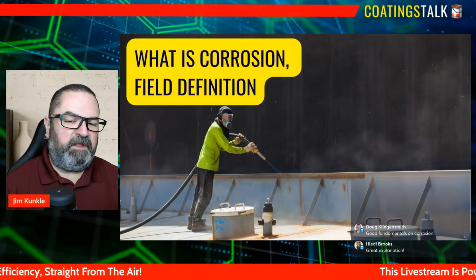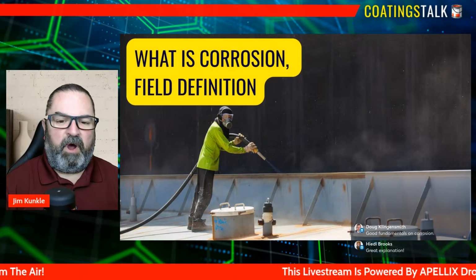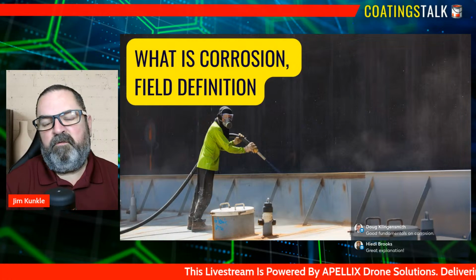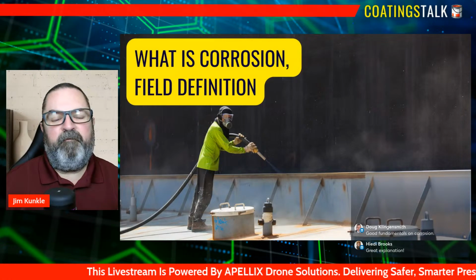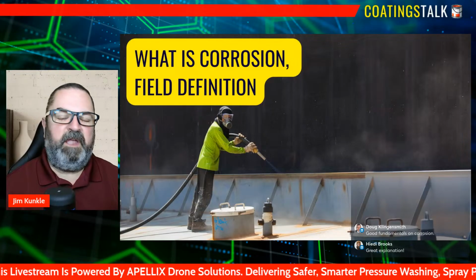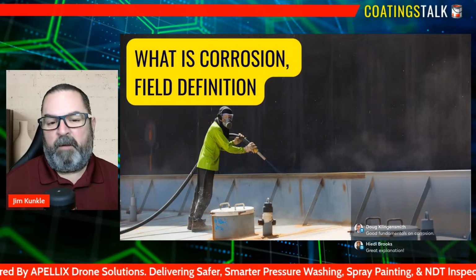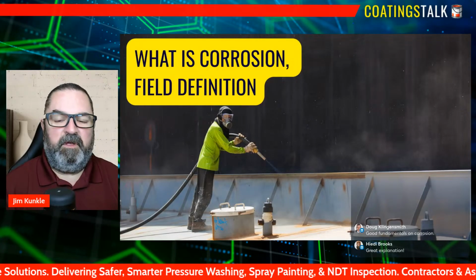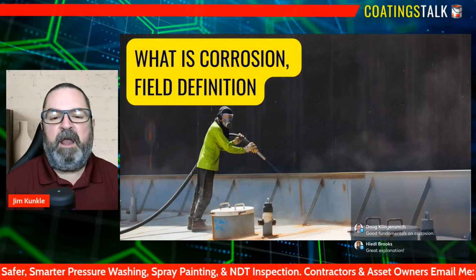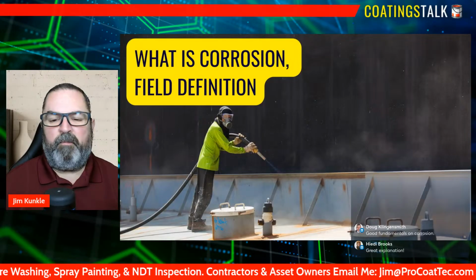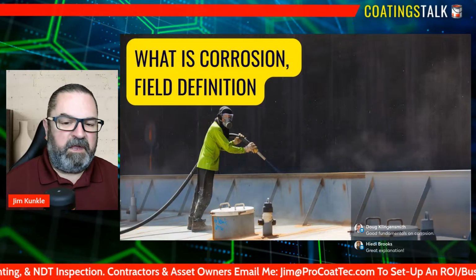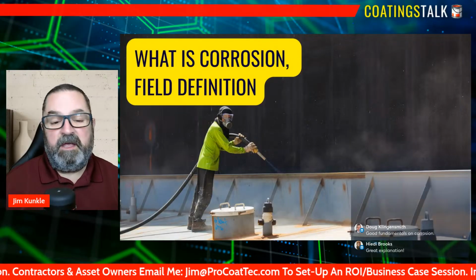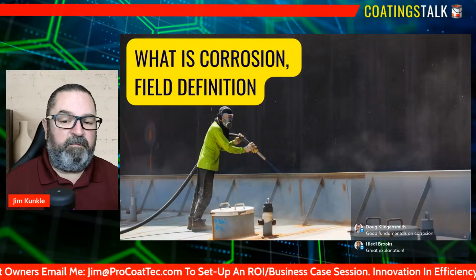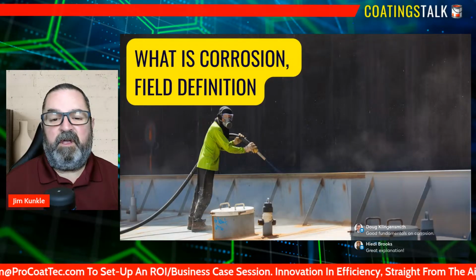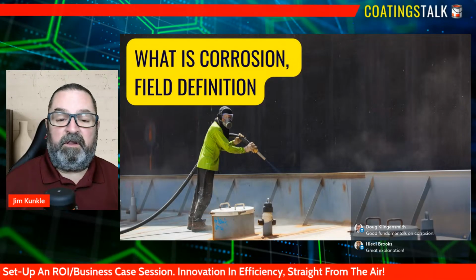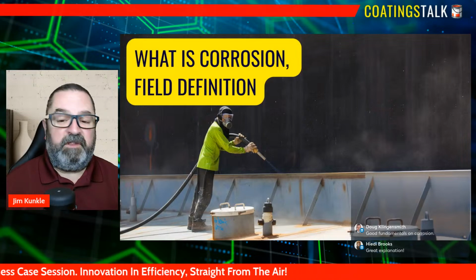Corrosion is not just a sudden event. It's a continuous process, and it's the field person's job to interpret it before it accelerates. There's also a tendency to believe that coatings alone stop corrosion, no matter the conditions. Coatings are powerful tools, but they're not a magic shield. Poor surface preparation, insufficient film thickness, contamination, or environmental extremes can compromise even the best coating system. When field professionals understand that coatings control corrosion rather than eliminate it, they approach the application and inspection with far greater precision and accountability.